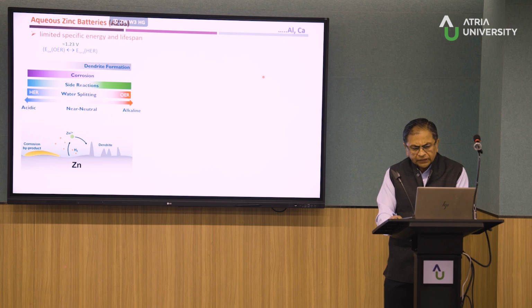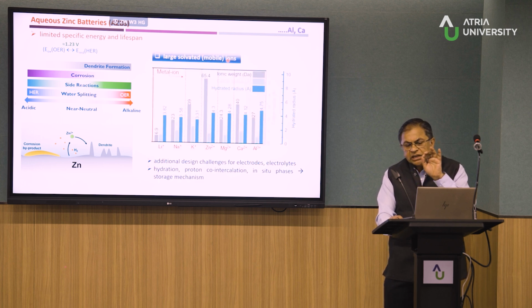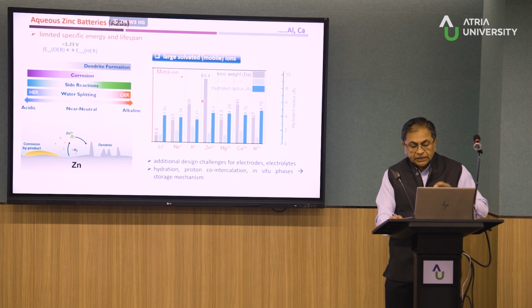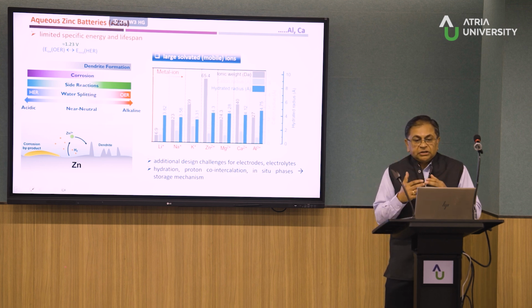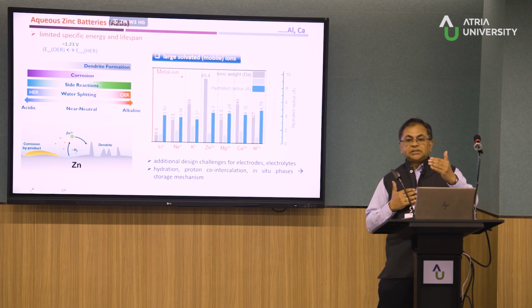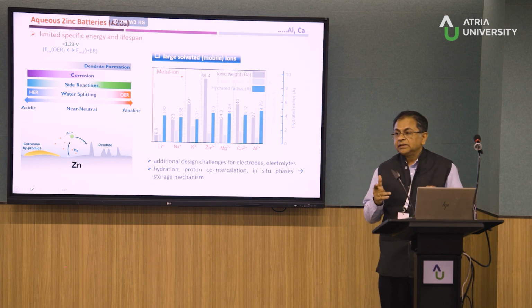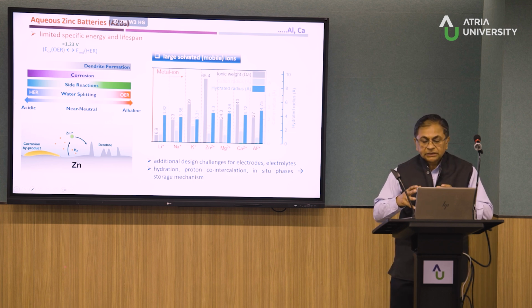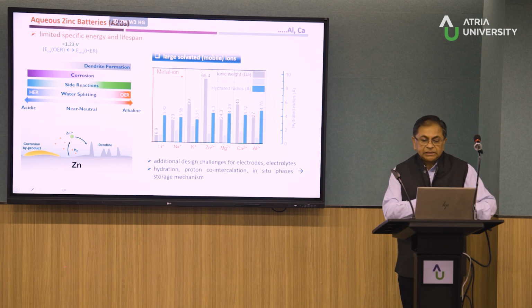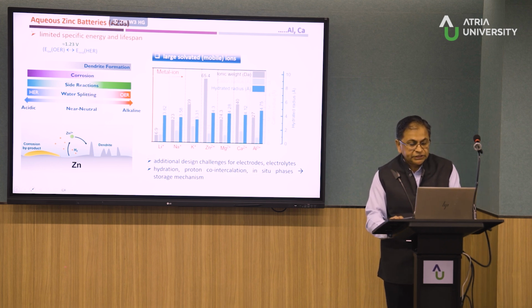The other problem with the aqueous is that you're actually dealing with large hydrated ions. As you can see, if you take zinc, the cation radius is 0.74, but the hydration radius is more than an order higher. So there are severe problems. If you have, let's say, an electrode where the interlayer spacing is double that, even then you would end up with problems because of the huge hydration drag which the ion takes into the cell during insertion and reinsertion.